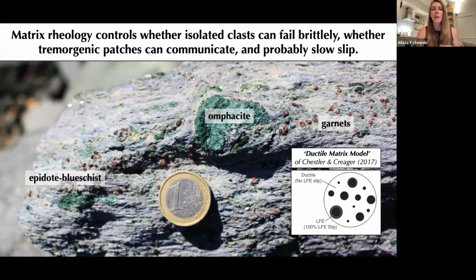So you can imagine these things are asperities, looking at this really simplified ductile matrix model from Chestler and Creager from 2017. Essentially, this is a heterogeneous patch of interface with these black circles here, which could potentially produce these low frequency earthquake slip, but it's surrounded by this more ductile white material. In this case, it's aseismically slipping, creeping interface. So these asperities can actually act as stress concentrators. And because they concentrate stress, that's why they can periodically release energy by low frequency earthquakes.